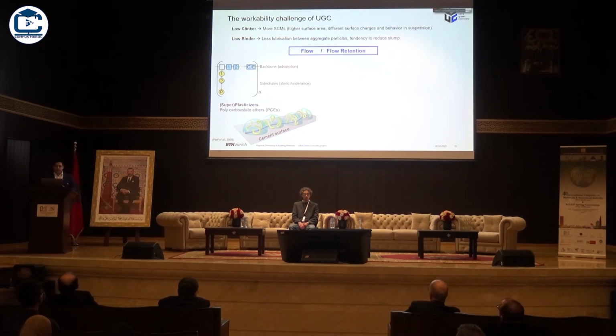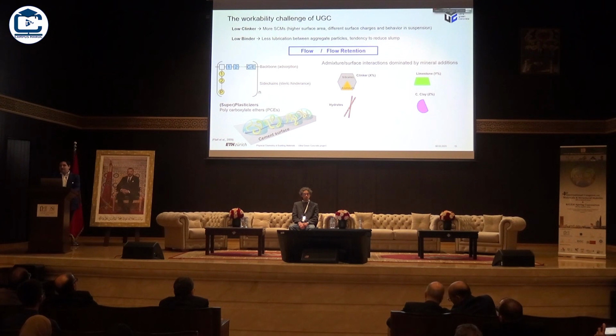So PCEs are these polymers that are in most advanced modern plasticizers and superplasticizers. They have a backbone that controls the adsorption on the surface, and they have side chains that basically provide the steric hindrance and therefore the repulsion between particles. In these blended cements, the situation is though a little bit more complicated. So we have this lonely PCE molecule entering the world and interacting with this LC3 or low carbon cement, and basically we need to answer now a question of where this admixture is adsorbing. We have much more surfaces than just the clinker, as in the case of OPC. Moreover, this process is dynamic, so there is a kinetic component that we need to consider in our equation.